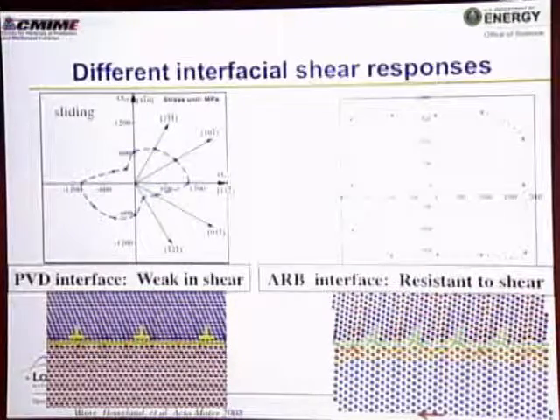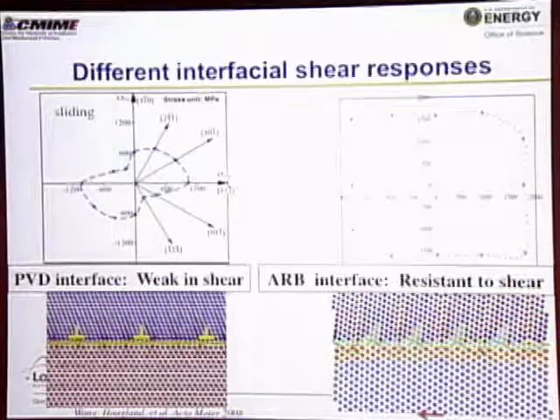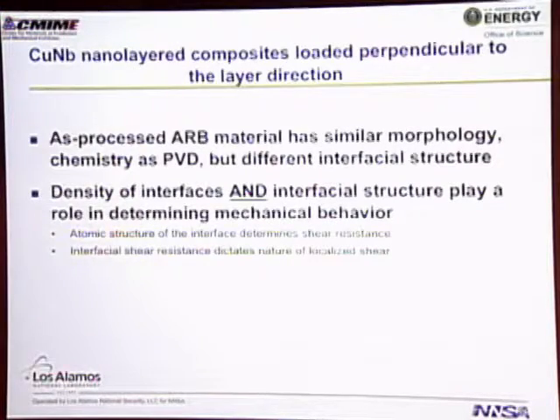The ARB interface, that roll bonded interface, is serrated. It locks things into place. The shear strength is extremely high, out here close to 2,000 megapascals or so. So what that means is that you can't slide this interface effectively at all. So that mechanism that we saw where you get a stable kind of deck of cards sort of sliding can't occur. So what we found here is that the roll bonded material has a similar morphology and chemistry, very similar types of layered structures, but the interfaces themselves are different. And what that does is completely changes its mechanical behavior.